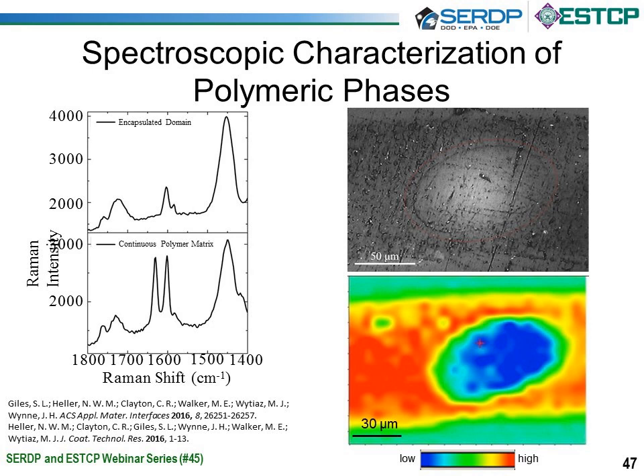We took this sample and we were able to acquire Raman spectra of both the domain, which was inside that sphere, as well as the continuous phase, and those spectra are presented on the left. The top is the encapsulated domain, the interior portion highlighted in the red circle, and the continuous phase is the spectra below. Notice that they both have peaks at 1600.